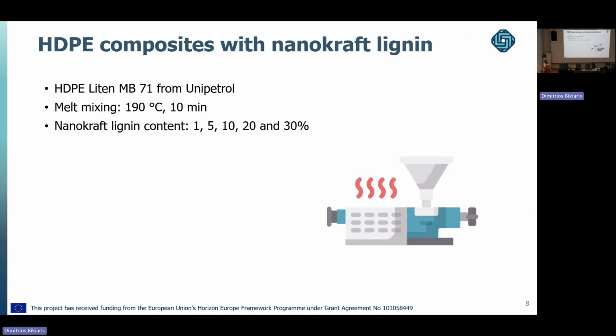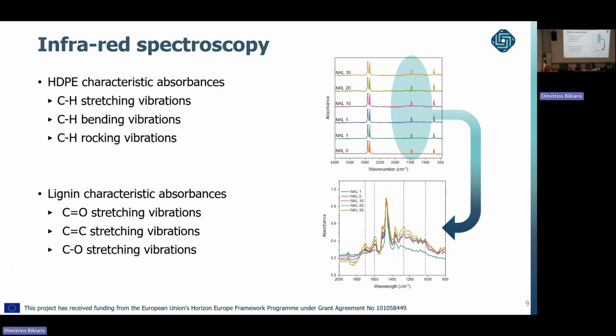Now, the composites were prepared by melt mixing at 190 degrees, with the lignin content ranging from 1 to 30%. I'll start with the results on nanokraft lignin and then move to the modified lignins. So the composites were studied by infrared spectroscopy. As you can see here, in the infrared spectra, we can see the absorbances of HDPE. And also, if we zoom in on the region which is here, for the composites which have more than 5% lignin, we can see also the characteristic absorbances linked to the presence of lignin.